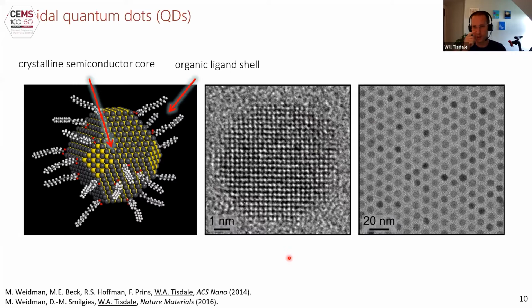If you zoom out in the electron microscope, you see this image on the right. This is a hexagonal close-packed monolayer of lead sulfide quantum dots. We did not template this in any way. These nanomaterials self-organized themselves into this hexagonal close-packing arrangement upon solvent evaporation.